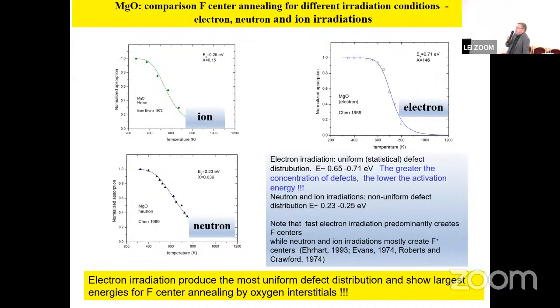This is just a first, good example: the MgO crystal. You can see here three cases: neutron, ion, and electron irradiated MgO. There is a huge difference in activation energy for defect annealing in this material, 0.25 and 0.7, quite a high difference. But this is understandable, because in the case of electrons, we produce defects randomly. There is no defect cascade and no defect interaction. But in the case of neutrons and ions, the situation is opposite. There is strong defect interaction, and this is probably the first reason for such behavior.